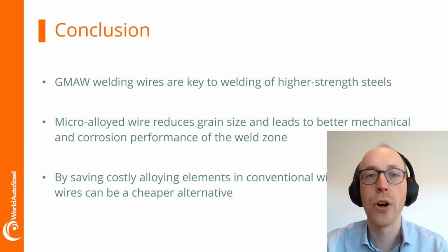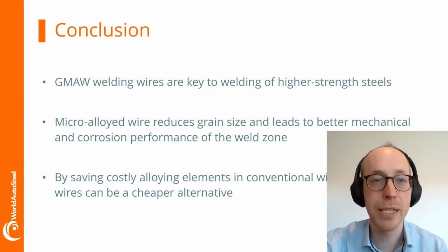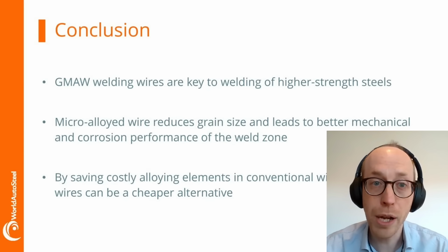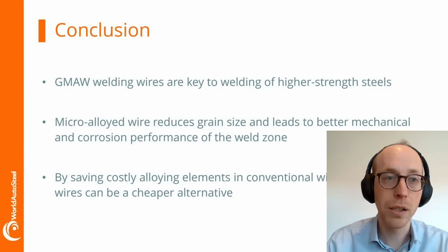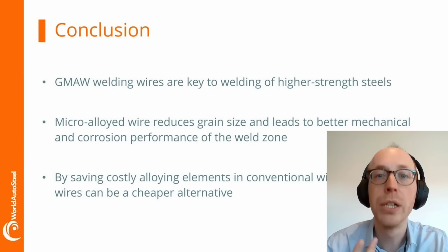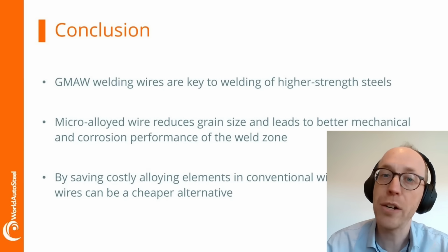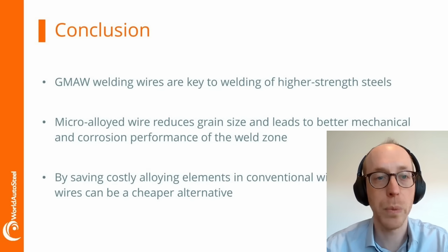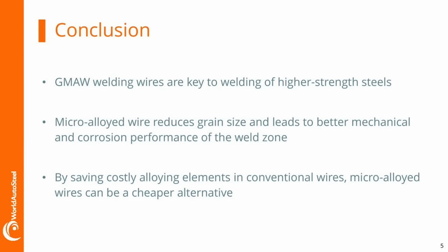So in conclusion, gas metal arc welding wires are the key to welding of higher strength steels. If we have a microalloyed wire, we can cause a finer grain microstructure, and that eventually leads to a better mechanical and corrosion performance of the weld zone. In addition, by saving alloying elements, so if we use a microalloyed wire rather than an alloying concept that uses, for instance, nickel, we can also cut the cost of the wire itself because we're using less alloying elements.